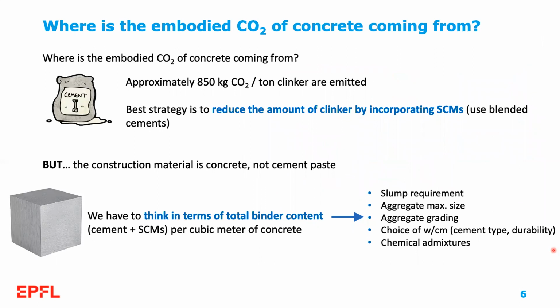The CO2 of concrete is coming mainly from the cement that is used as a binder to connect the aggregates in the material. Approximately 850 kilograms of CO2 are emitted per ton of clinker produced. In this sense, the best strategy, and this is the focus of most of the research on sustainable Portland cement in the last decades, is to reduce the amount of clinker by incorporating what we call SCMs, or supplementary cementitious material. In short, we need to use blended cements.